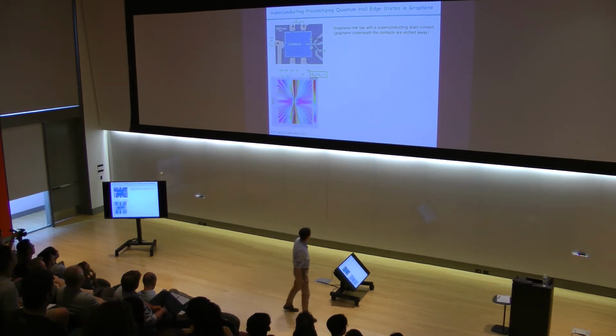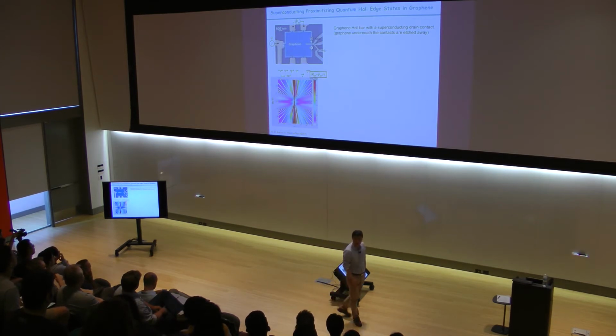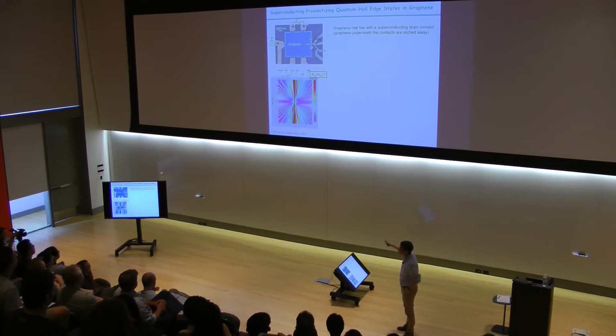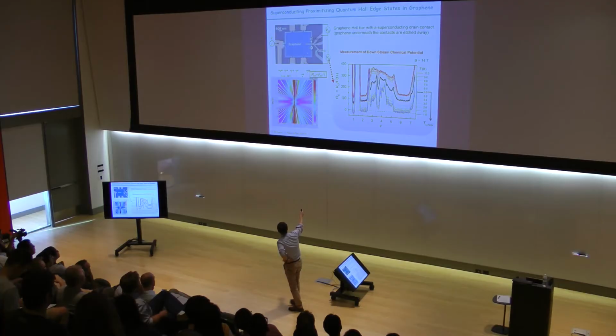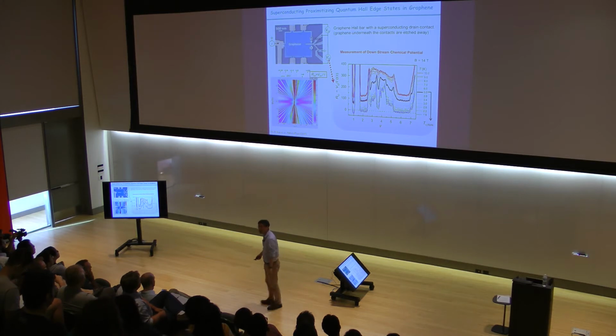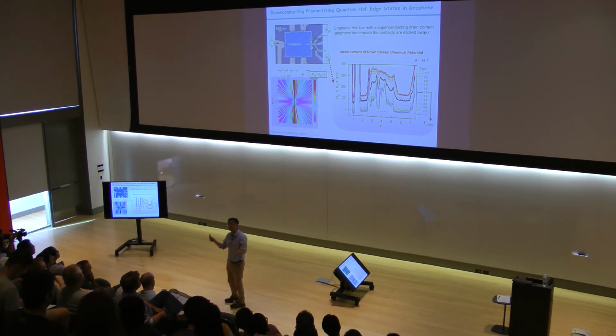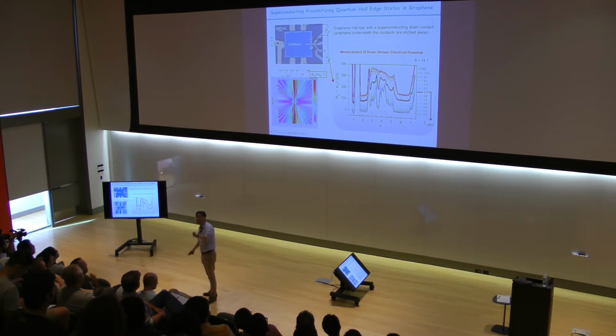In our experiment, we found that this sample did show a nice quantum Hall effect down to, say, a few Tesla, nicely developed, with all the nice quantum Hall plateaus. But not only that, when you carefully measure the chemical potentials of the edge states, we realized the interesting part. Some of the chemical potentials we measure in the circuit turn negative. That's a very weird moment, because we applied only positive voltages, 0 to positive voltage, in these circuits, but at some point in your circuit, you start to pick up negative voltages. Classically or semi-classically, it cannot be explained.